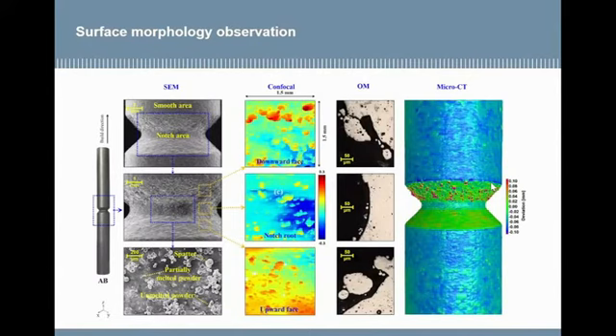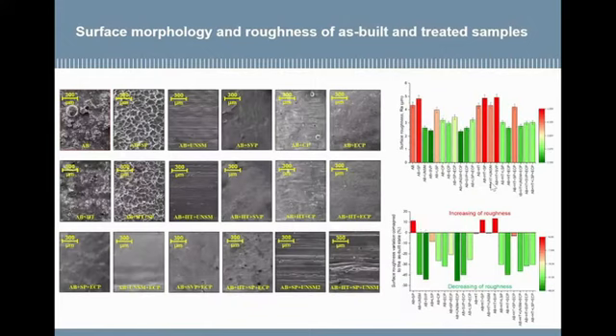Here you can see the morphology of our samples, what I was talking about, again, the irregularities having a very high density of partially melted powder spatters and/or agglomerates on the down skin, on the notch area, and that which was having the highest surface roughness in the notch area, followed by the notch root and then the upper skin. The treatments were able to reduce considerably the surface roughness.